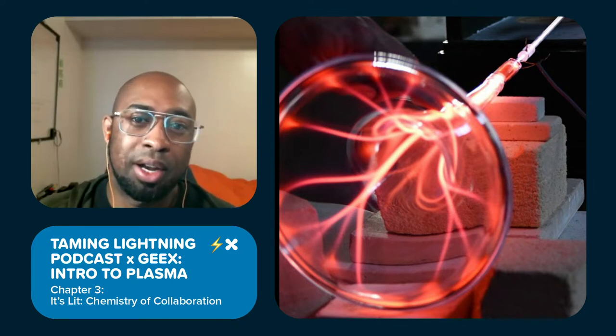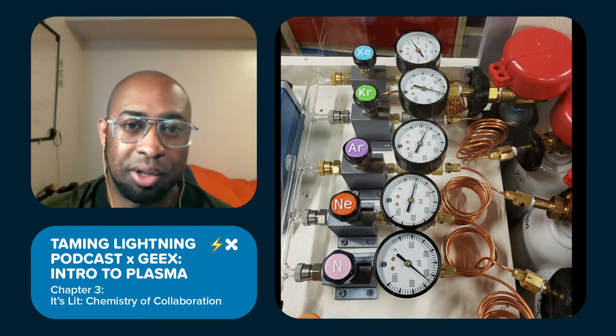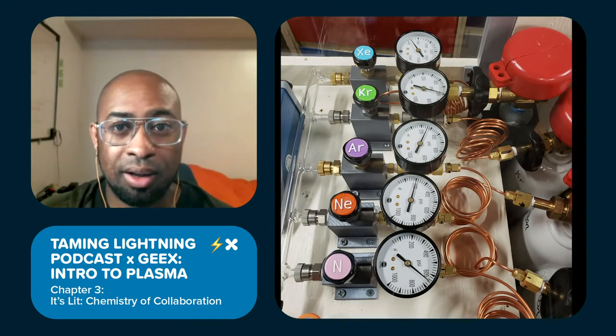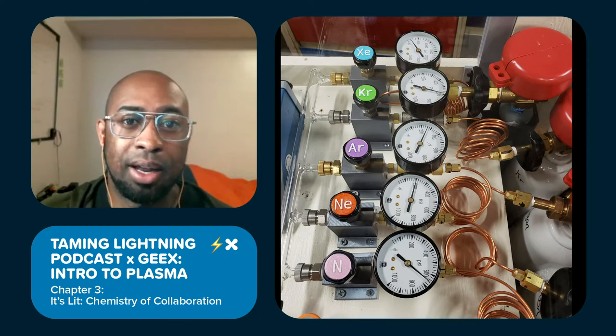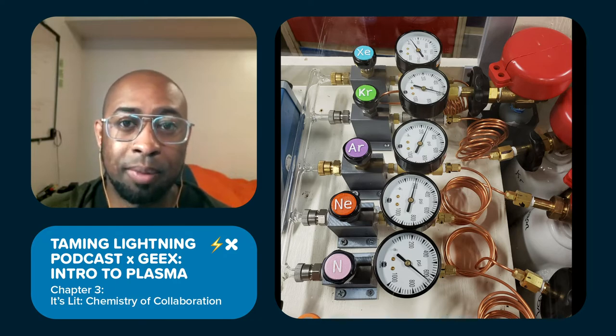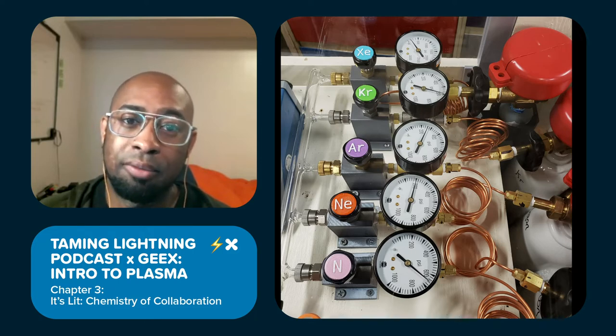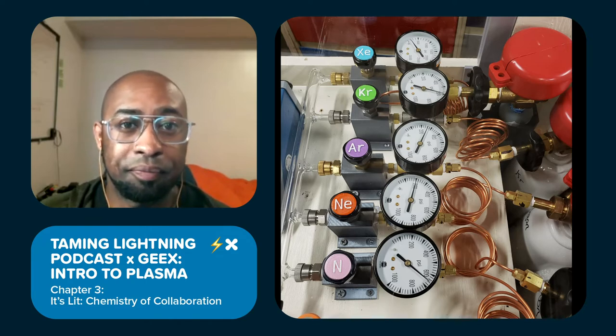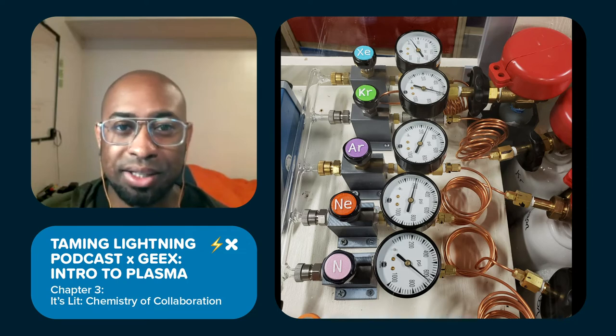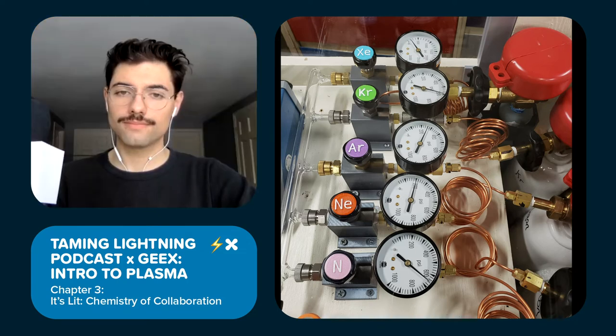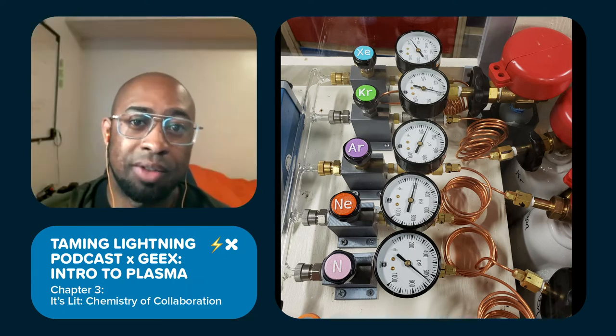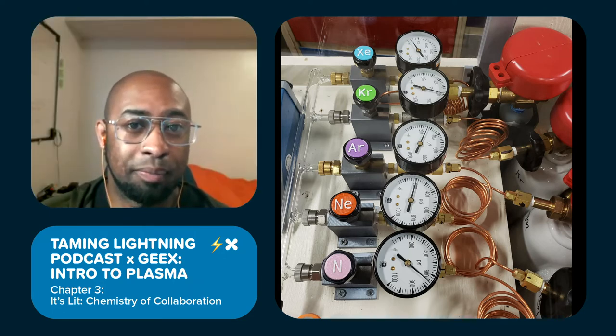We can now begin the initial gas fill. Prime the gas fill line. Is there pressure in your tank? And is the needle valve and any of the other areas of your manifold closed off? Make sure also the reservoir, the gas fill line, has pressure within it and that your needle valve is nice and closed. Slowly let the neon of 5 to 10 torr into the manifold slash vessel and close the needle valve. Adjust as necessary. Turn on the transformer to see results and then turn it off and add 5 to 10 torr at a time until you reach your desired outcome.